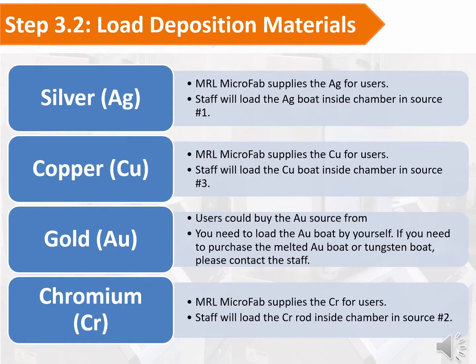Usually silver, copper, and gold boats can be loaded in cells number 1 or number 3, and the chromium rod is loaded in cell number 2. Please check the evaporation boat to ensure that the cell's material is at the proper level for your deposition process. Due to the limited capacity of the tungsten boat and rod, the thickness limit is 200 nanometers per boat for gold, silver, and copper, and 40 nanometers per rod for chromium.